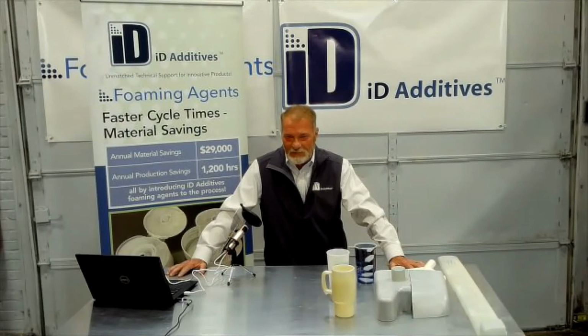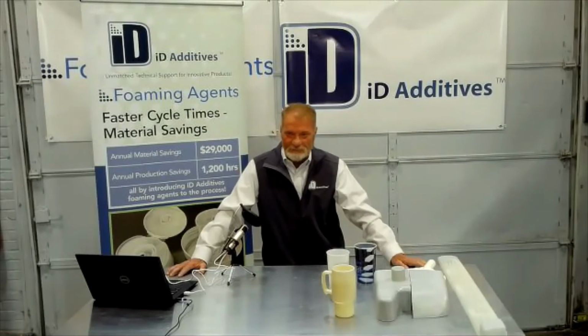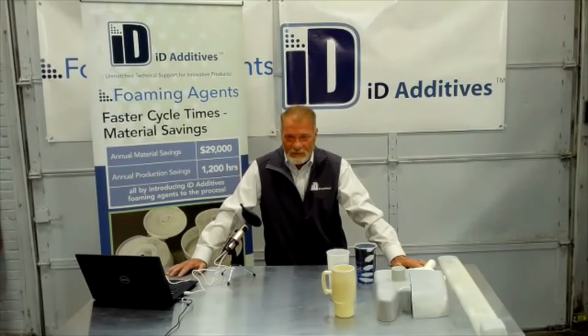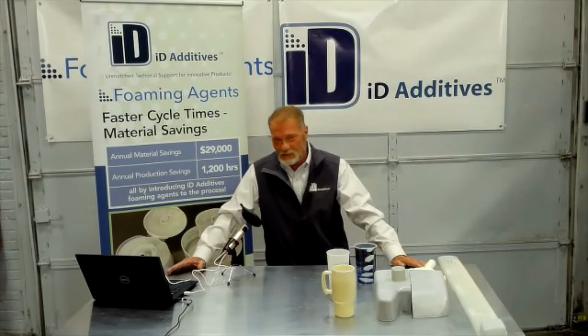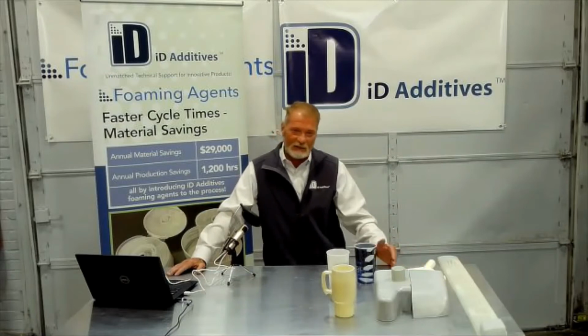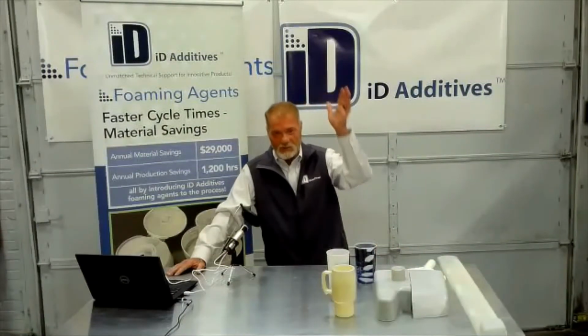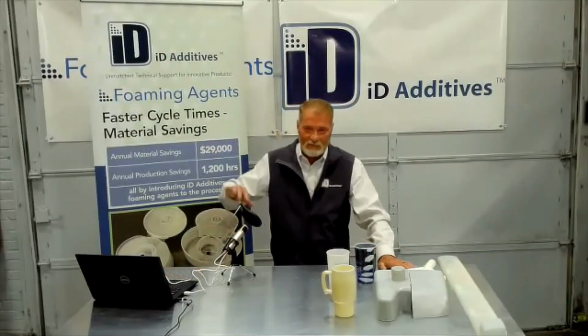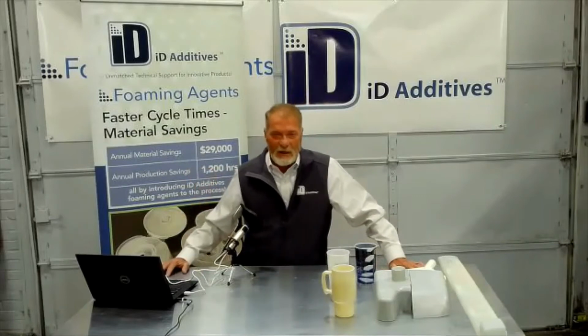Next question is, you mentioned the exothermic creates nitrogen gas. What type of gas does an endothermic material create? That's the gas. Nitrogen is an exothermic. CO2 is an endothermic. Nitrogen gives off an exothermic reaction and generates heat. Boom, you get all the gas at once. Endothermics go off in a slope. They absorb heat. That's pretty much the difference.